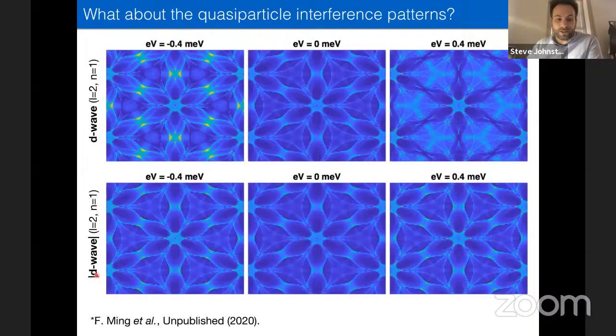I can check that by just introducing the absolute value of the gap. So I remove all the phase information by replacing delta with the square root of its modulus squared. And what you see again is that these flower-like petals just disappear as soon as you do that. As soon as you remove the phase information from the superconducting gap, they vanish. And so we can repeat this for the D-wave or the longer range hopping d+id pairing, and we always get these petals appearing only when we have a chiral order parameter. If we put any other order parameter into the simulations, these star-like patterns don't show up in the QPI images.